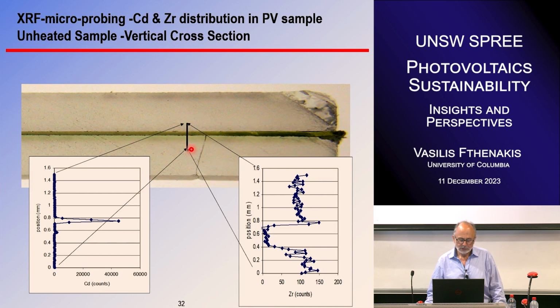And the fluorescent analysis, as you know, is a photon that ionizes the atom, and then you have the hole that dissipates at a certain intensity and a certain energy wavelength. Cadmium emits at about, I think, 23 kilo electron volts. So you have the signature of what is emitted as the atom decays from the ionized state, and the intensity of this peak gives concentration. Here it is about 45,000 counts. This is a concentration, and this is the signature of cadmium here in the center.